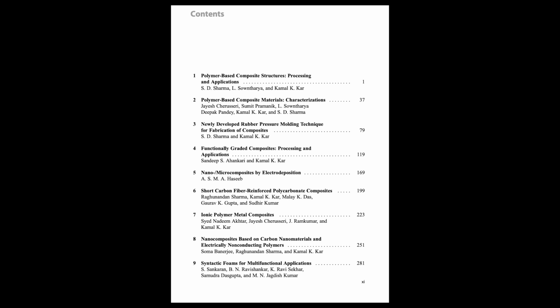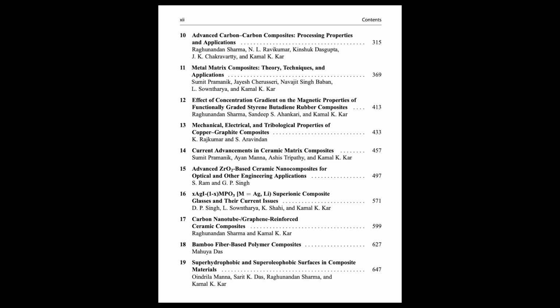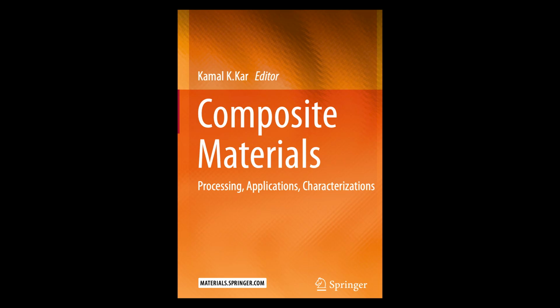Any other impact tests? The notched Izod test is mentioned, especially for composites with specific fiber end shapes. Results depend on the matrix, the fiber ends, fiber length. That sounds complex. It is. The sources break down toughness into components like energy for deformation, for pulling fibers out, for creating new crack surfaces. Equations 2.20 to 2.22 cover this. Fiber pullout sounds important. It often is, especially in thermosets with carbon fibers.